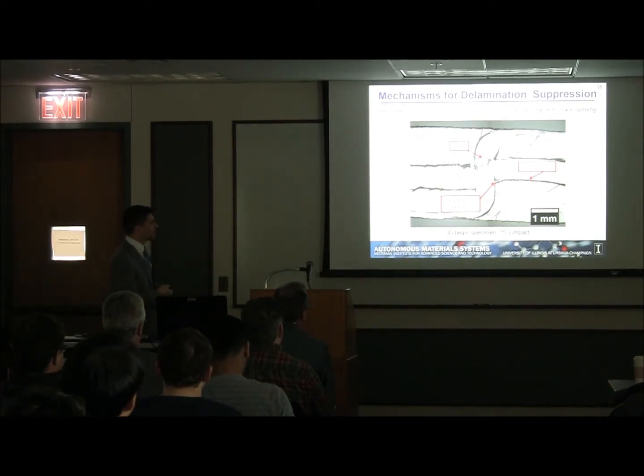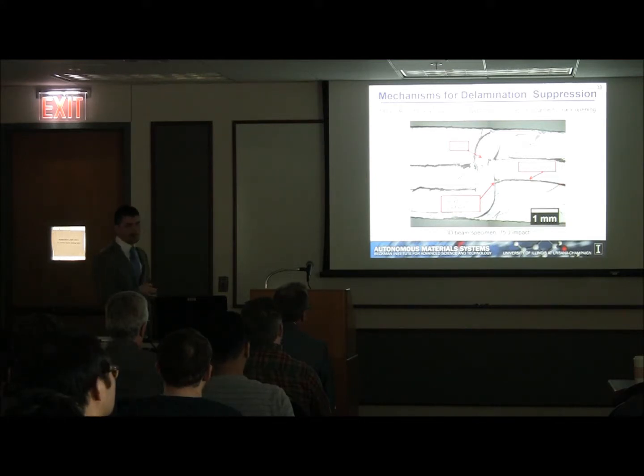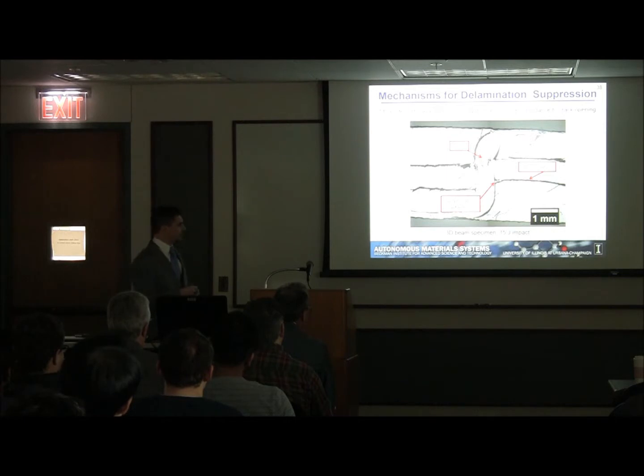In this image we have a cross-section of a composite with a through-thickness tow running through our 3D weave. So this is our Z tow again. One of the mechanisms that limits the delamination is what we call delamination deflection. As these delaminations grow, they eventually have to run into this through-thickness tow if they want to propagate any further. However, this deflection downwards or upwards, which occurs at the Z tow, requires energy. And that energy is not going into creating more free surfaces, it's going towards deflecting the delamination downwards or upwards. So that's one mechanism that limits the delamination opening.